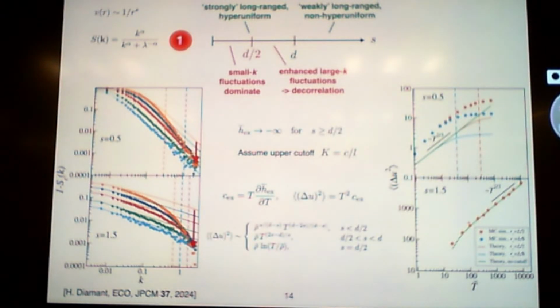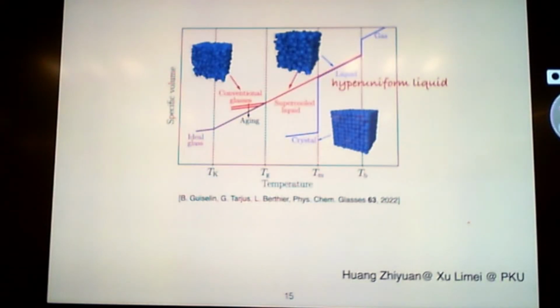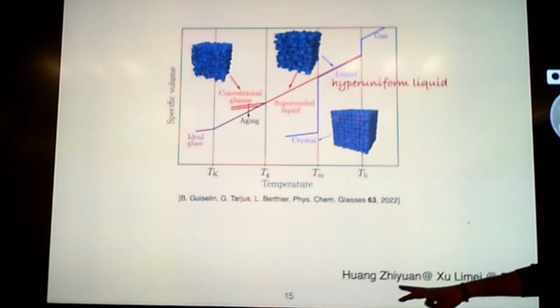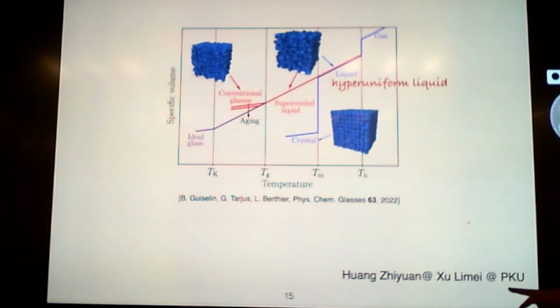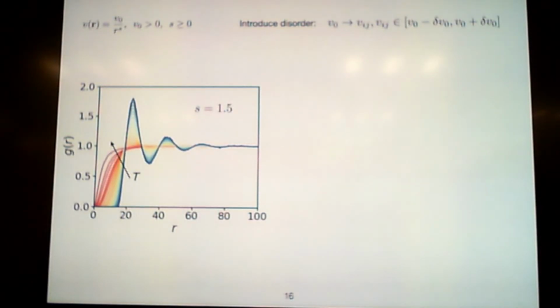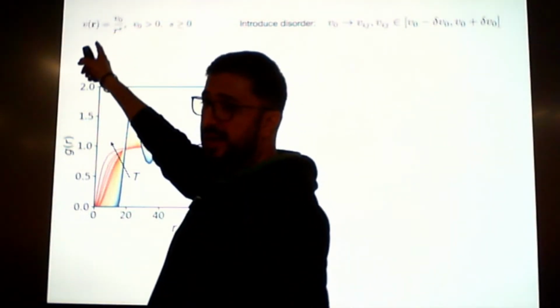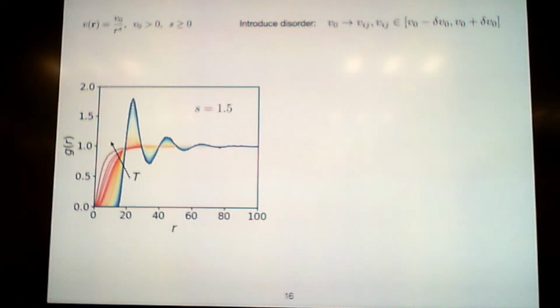Now, I'm taking this system, I'm cooling it down to get a glass, okay? And this is partially also with the student Huang Zhiyuan from the lab of Xu Limei at Peking University. Okay, so going back to your question, we have long-range interactions, so the liquid is hyperuniform, or the fluid, because in this case we can't really distinguish between gas and liquid because there's only repulsion. One way to create a glass is to quench it very quickly, but in the computer, no matter how quickly you quench, you always get a crystalline lattice if you don't have disorder.